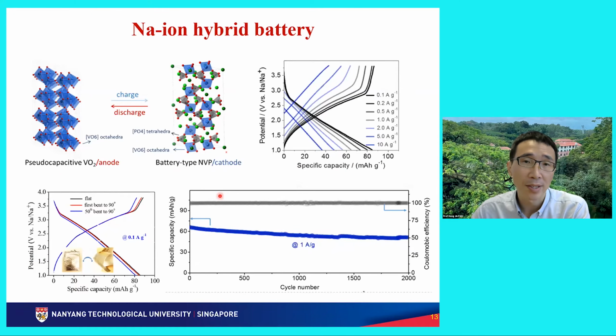The mechanism is quite similar. On the negative side is a pseudocapacitive vanadium oxide on the three-dimensional carbon flakes. On the right side is NVP, battery type cathode. So the whole battery is still rocking chair, but it's a hybrid battery mechanism because the whole battery manifests a capacitive behavior. That means the voltage has a linear decrease with respect to the discharge time. So this is a typical feature of capacitive behaviors.